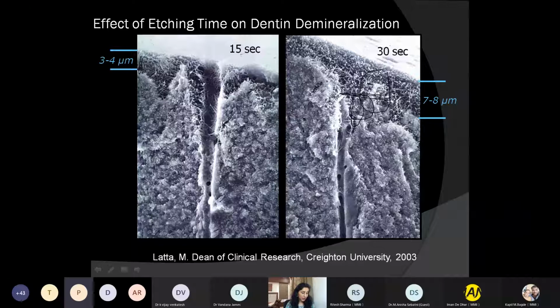So what will happen? This unsealed dentinal tubule will permit dentinal fluid flow during thermal and tactile stress, which will in turn stimulate the nerve fibers in the pulpal tissue. Thus, stimulation is the primary source of post-operative sensitivity, and the patient will experience pain while eating or drinking hot or cold, or when just simply biting on restored teeth. So always remember that the etching time for total etch technique is 15 seconds for enamel and for dentine not more than 15 seconds, in any case.